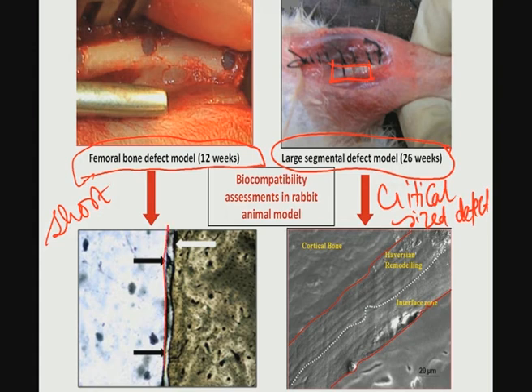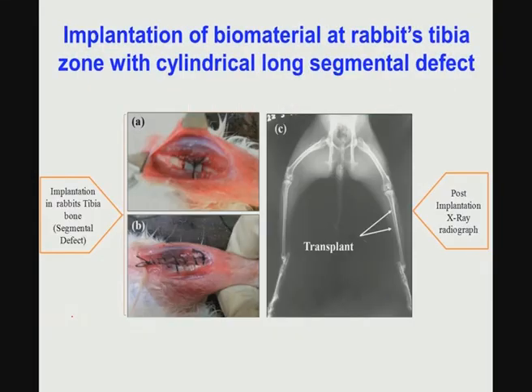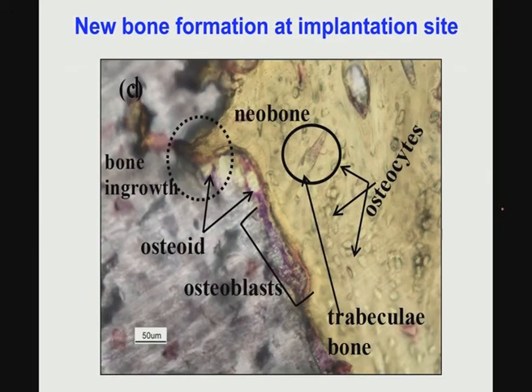Then after that you see these histology images and so on, and this is your SEM image. In both the cases you see that there is neobone generation, and you can say that is Haversian remodeling, and this is clearly shown at the interface zone, and this is your cortical bone, that is the host bone. Here also it is a cortical bone, and then another part is your normal implant. This is the case of implantation in the segmental defect model. Here you can see that it is placed with sutures and so on, and this is how the implant looks like in the X-ray radiograph in the rabbit model.